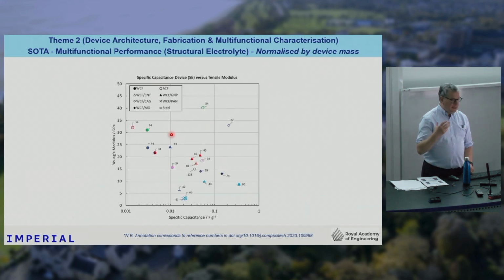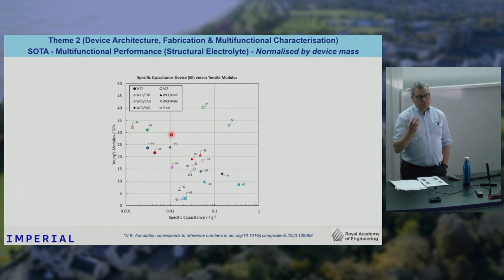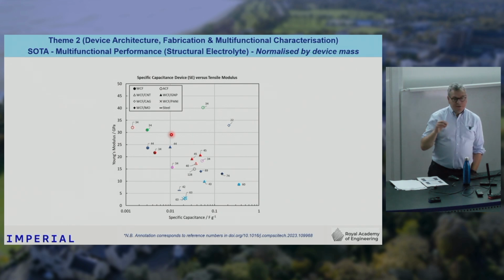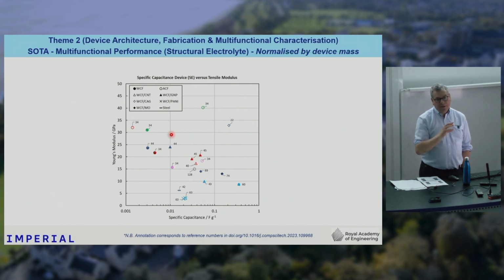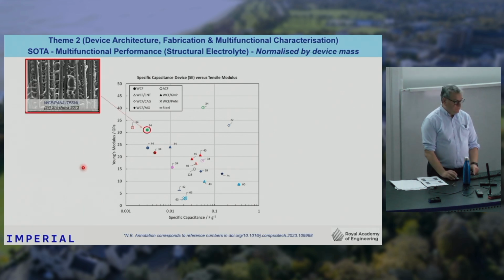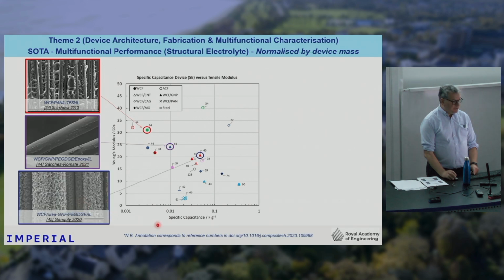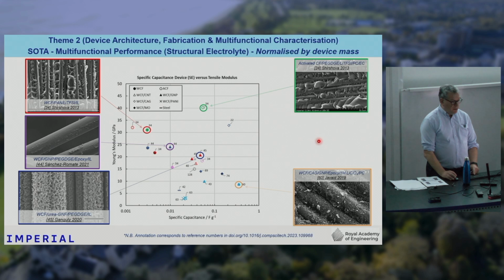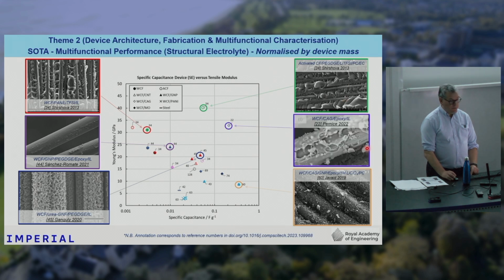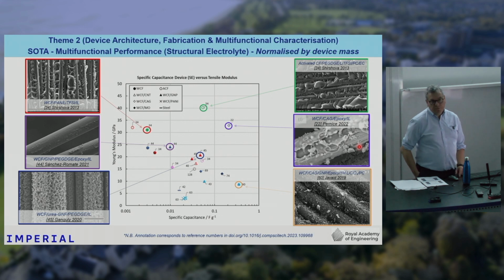Perhaps what's more interesting is what we call a structural device that uses a structural electrolyte and it's normalized by the device mass. So when I looked at all the papers that are out there, some people only give the performance normalized by active mass or electrode mass, and some people only report device mass. And so I couldn't compare those different data sets, which was very frustrating. But this is showing you some of the different work that's been done in this area, the different types of chemistries that people have used. And then this is showing some of the data that we've produced, the carbon aerogel. And that looks to be one of the best performing devices that are out there.